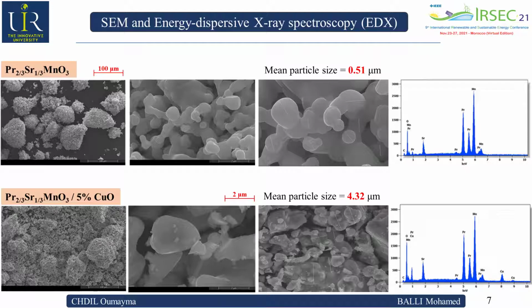In the following figures, we present SEM micrographs of the two samples and also the EDX spectra, which indicate the presence of different chemical elements. The copper additive effect is really apparent in the composite material micrographs, where the mean grain size is increased from 0.5 micrometers to 4 micrometers.